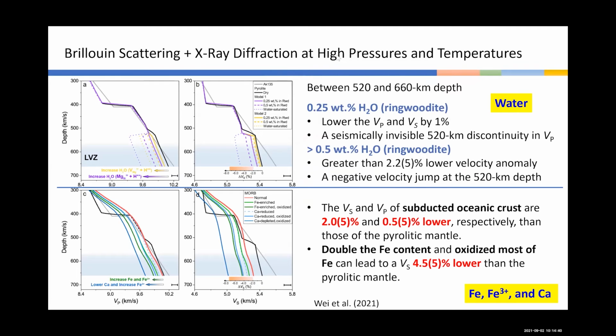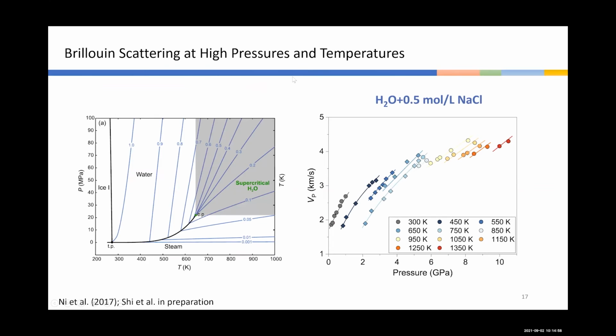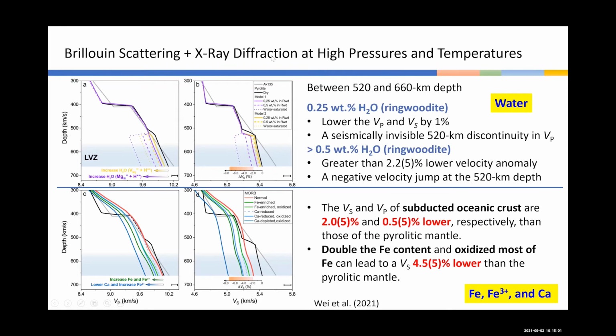This figure is a little bit complex. On the left, the top panels A and B are our modeling results, where we try to understand the influence of water on the sound velocity of the bottom transition zone. We can see here the black line represents the sound velocity of the dry pyrolitic mantle. We can clearly see the 410 kilometer discontinuity and the 520 kilometer discontinuity from our mineralogical modeling.